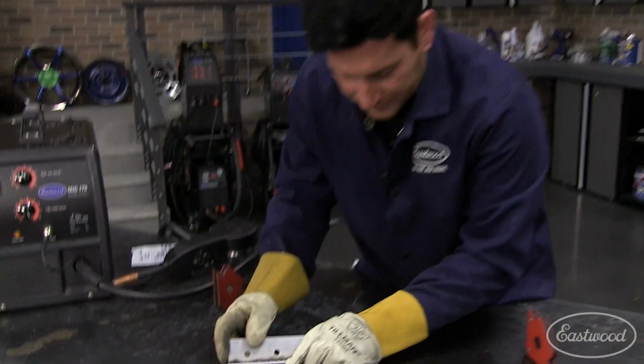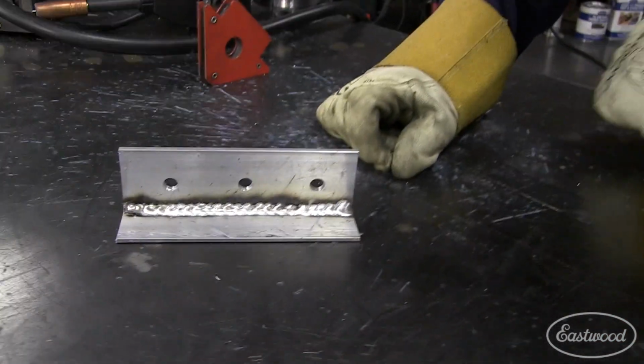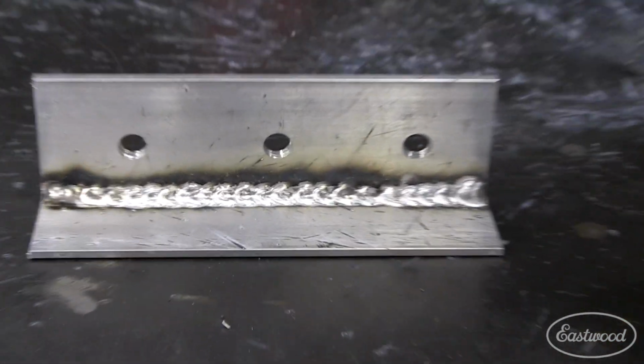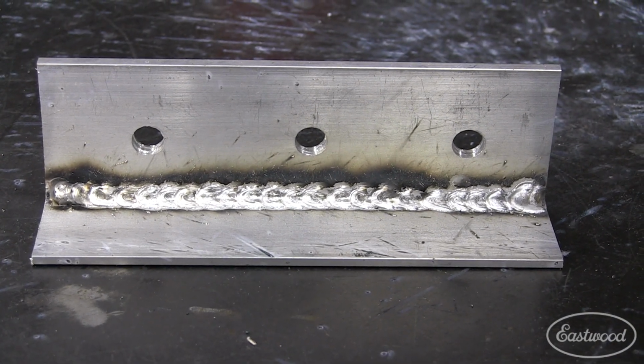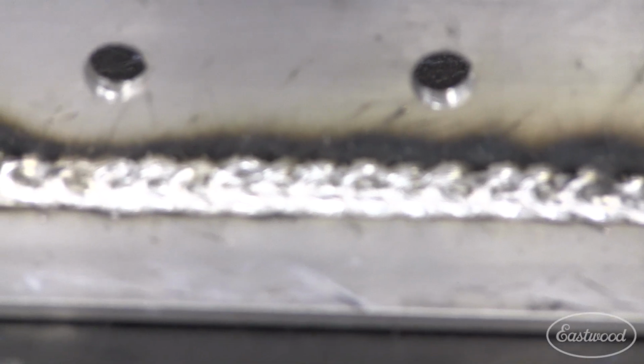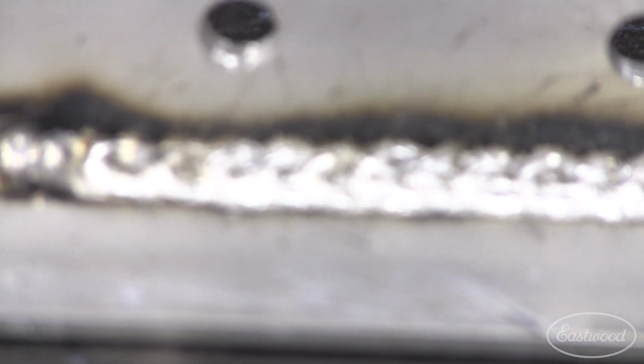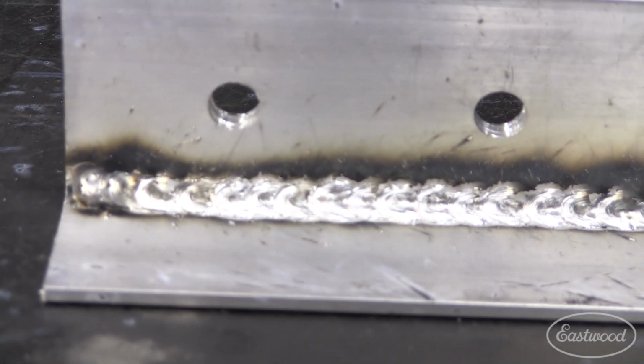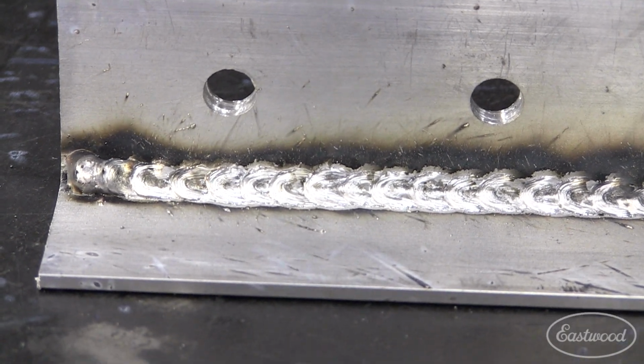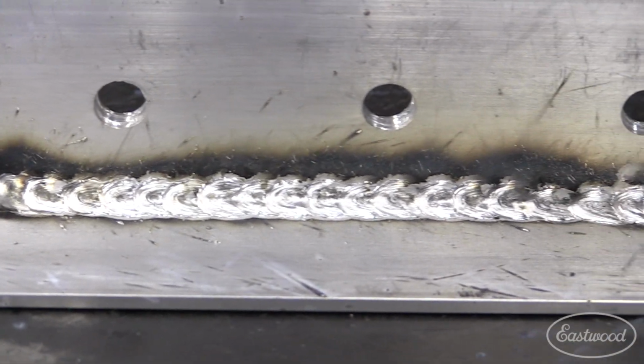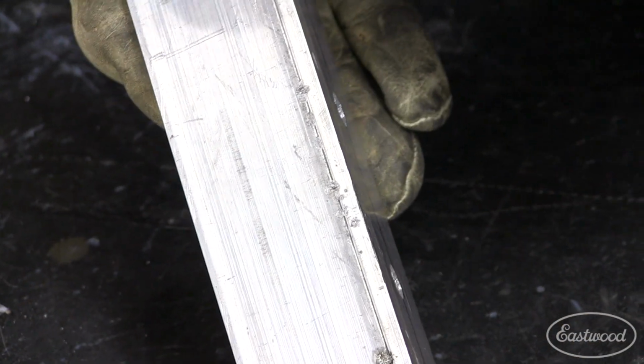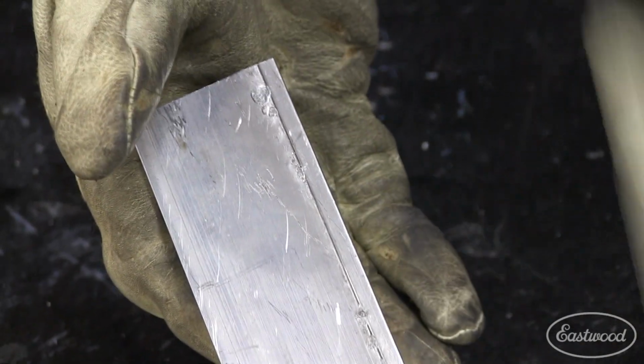So here you can see, before I've wiped anything down, what it looks like. You can see there's the black soot around the outside edge there. That's just the dirt and contaminants that are popping off. It's not nearly as clean of a weld as you would see with TIG welding. On the back side, you can see this is pretty warm here. We were dancing around burning through there. You can see some little spots where I was starting to get all the way through. So that's what you're fighting that whole time.